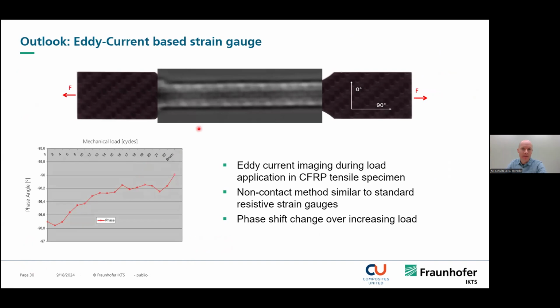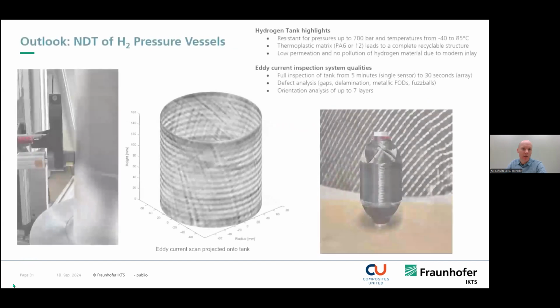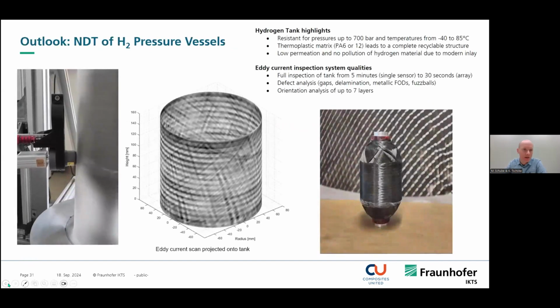So here we see eddy current based strain gauge. These are eddy current scans that were acquired during the tensile test, and you see a slight contrast change, and this occurs because of the phase change over increasing mechanical loads. And with my last slide, I will hand over to Kilian.